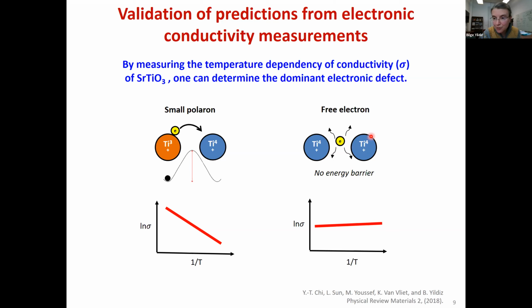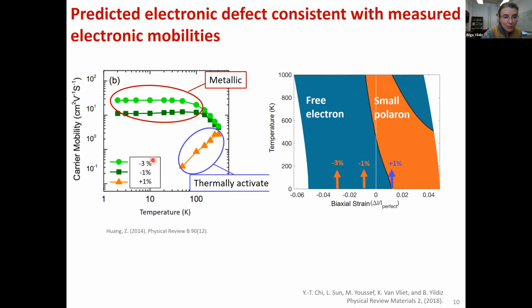Whereas if the free electron is dominant, this is not an activated process. In fact, with increasing temperature, there is further scattering. So we see either a flat or a very shallow slope in the conductivity as a function of temperature. So now if we examine the experimental literature that reported the conductivity in strontium titanate with different strains, we can observe these different regimes of slopes.